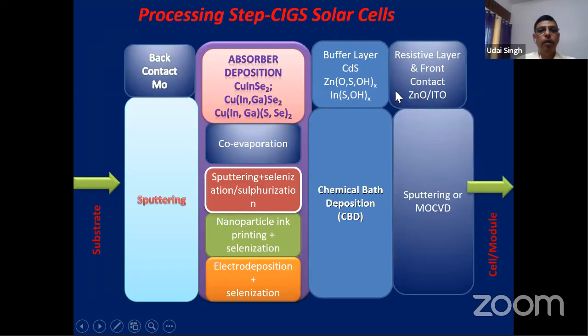Skip this. So if you see the processing steps, when you're trying to make the device, the back contact is mostly done by the sputtering technique. Then you have the absorber deposition, copper, indium, gallium, selenide. You can do it by co-evaporation. Co-evaporation means you are trying to evaporate all four materials simultaneously. The other method is sputtering plus selenization. So you sputter the copper, indium, gallium, and then in selenium you selenize it.